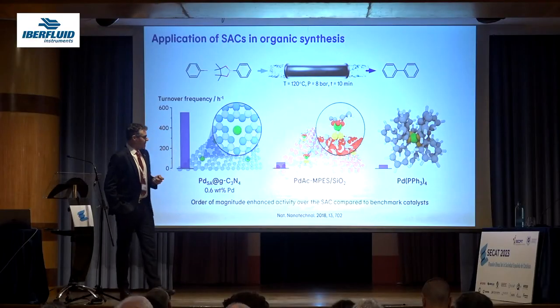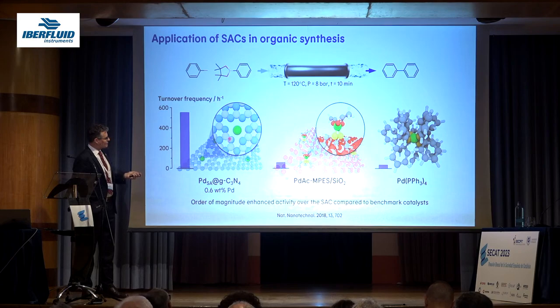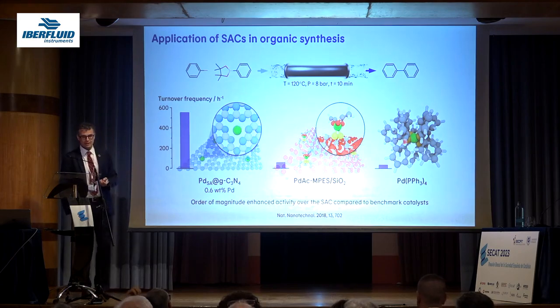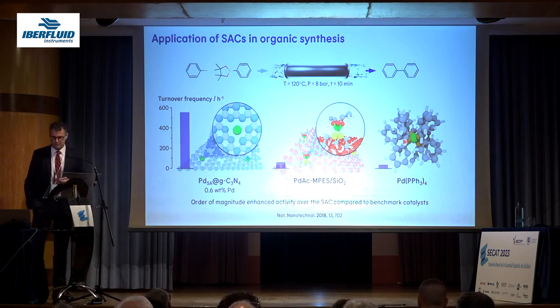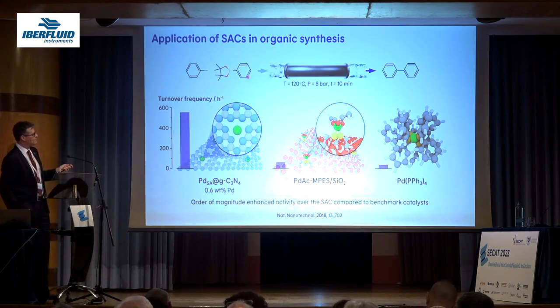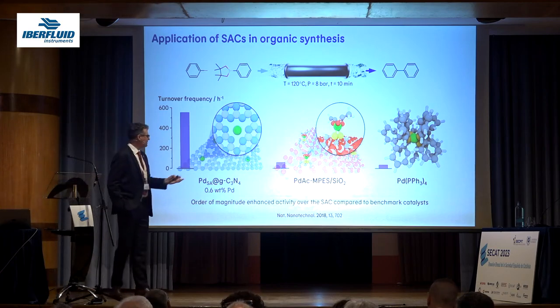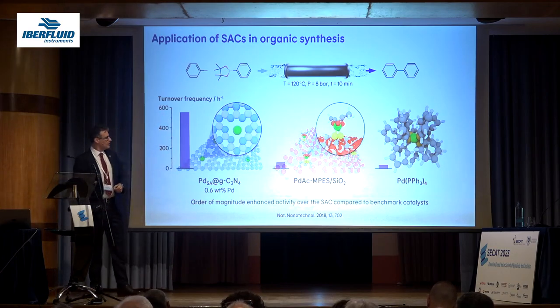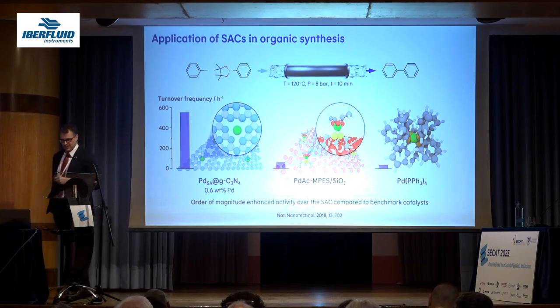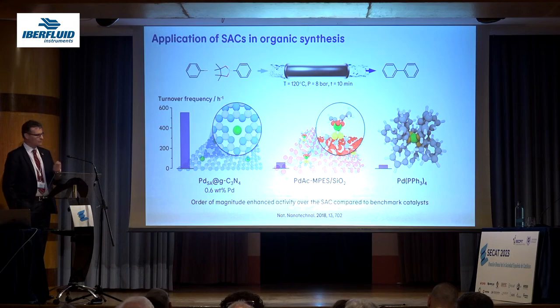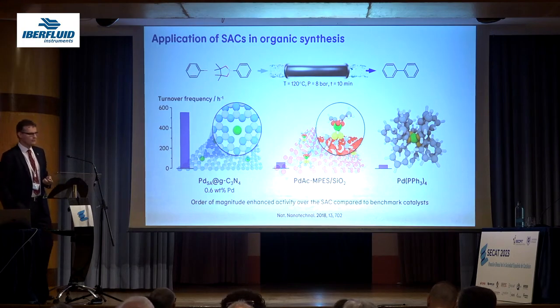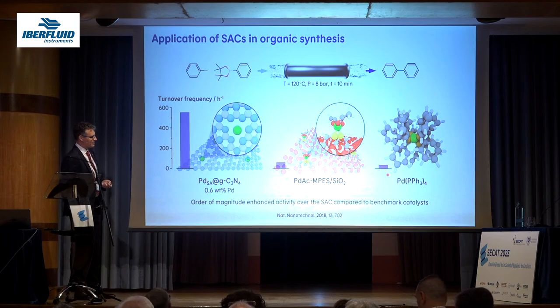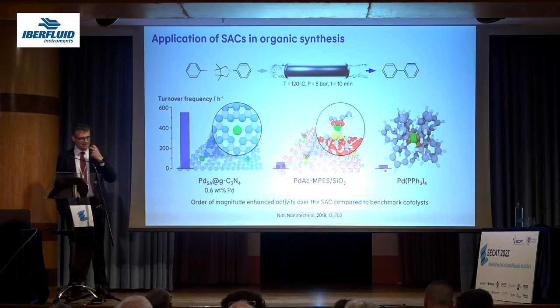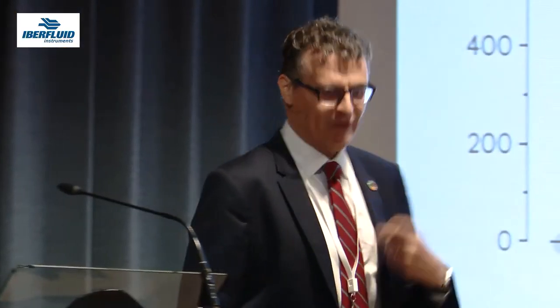And because of similarity, so this is a single atom, and this is a phosphine, typical catalyst for many organic chemistry transformations. So we tried this in Suzuki coupling, very easy reaction, and then we found that the turnover frequency of the single atom per amount of metal, very well dispersed, as single atom indicates, is about 1 order of magnitude higher compared to some of the materials that actually are commercially used in some cases. And this is another reference, which is a stabilized organometallic complex grafted on a silica. So very superior performance, very nice.